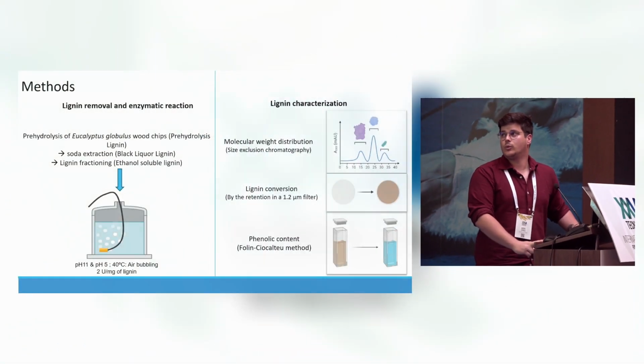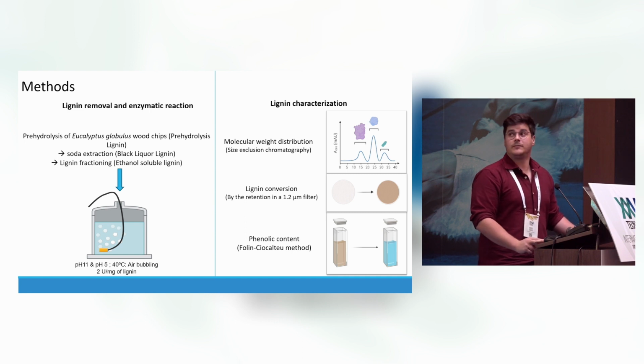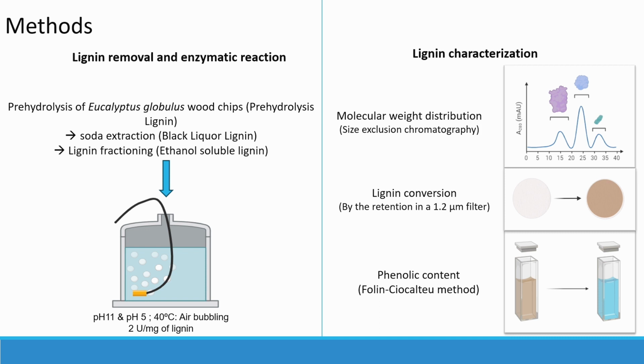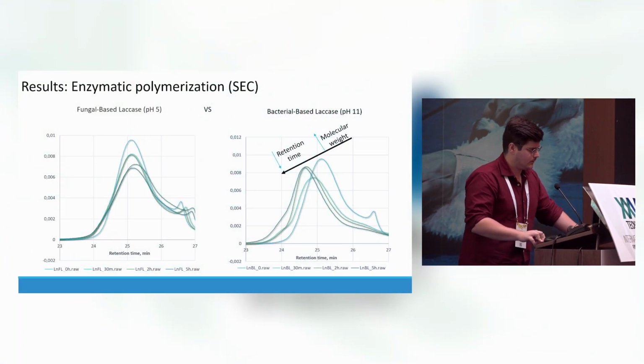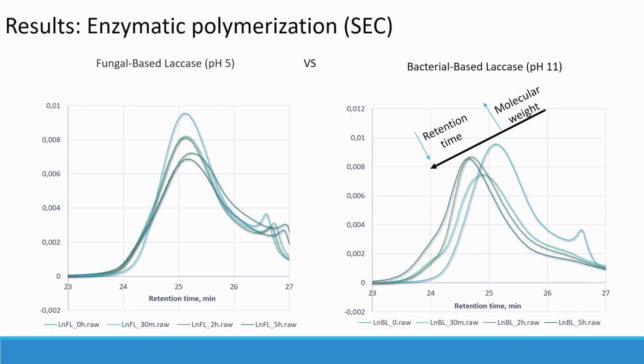Regarding the characterization, we analyzed the molecular weight distribution to see if the lignin is polymerized or if there's a decrease or increase in the molecular weight distribution. We also analyzed the lignin conversion, so we filter the solution after the treatment and analyze how much material is withheld in the filter, and we also studied the phenolic content. I will show more about the phenolic content, but it measures the hydroxyl groups that are available for the reaction.